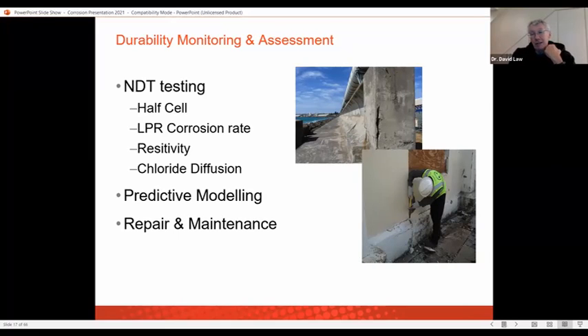Well, we can look at what's called half-cell potentials. That is, we can look at what that steel potential is that we talked about in the Pourbaix diagram. And from that, it will give us an idea of whether it's passive or whether it's corroding. We can do what are called linear polarization resistance corrosion rate measurements. We can get an instantaneous rate of corrosion.